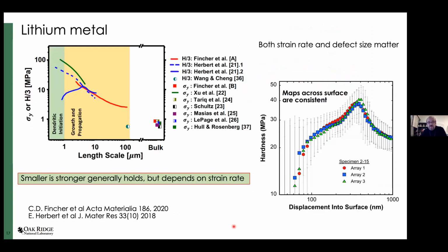As you go down in length scale, however, things are slightly different, and the general rule of smaller is stronger applies here as well, with some exceptions. So this is a plot which shows yield stress, or using the Tabor equation, 1/3 of the hardness, to compare results from nanopillar compression and results from nano-indentation. So this is all compiled from different publications, and nicely shows how the strength of lithium increases as you go down in length scale.